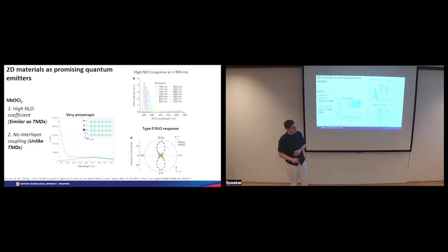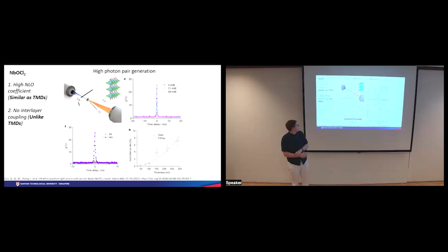With this one, for example, if the single layer interaction length is not enough to produce photon pairs by down conversion, when you stack enough layers together, you would still be in the subwavelength range, but you would have enough interaction length to actually produce photon pairs. So what they showed in this paper is that it's actually quite efficient in photon pair generation, and it scales well with the thickness.